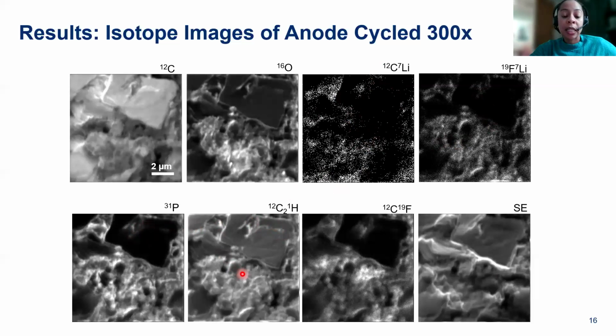So this is actually a very good result, because this corroborates previous data that says that the SEI on the cross section of the carbon materials is dominated by fluorine, and the basal planes, these flat planes, are dominated by more organic materials.